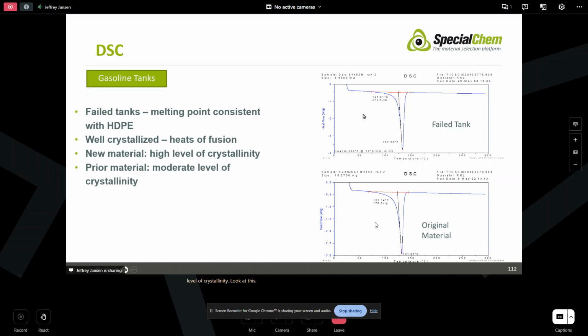If you look at this on the second heating run, our material has a heat of fusion of 212, and our original material 179. If you were talking about density of high density polyethylene, this is probably a 954, 956, and this is a 948, 947 probably. That kind of difference is huge for high density polyethylene.